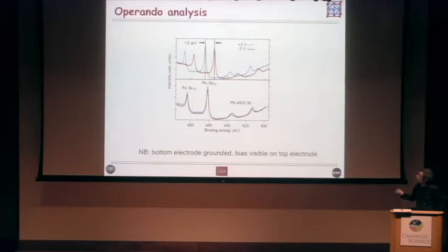Here are the raw data. The two bias states we used were +3 and -7. That was because, as you remember from the electrode characteristic, there was a 2-volt offset. So these values are actually symmetric around that measured butterfly loop.